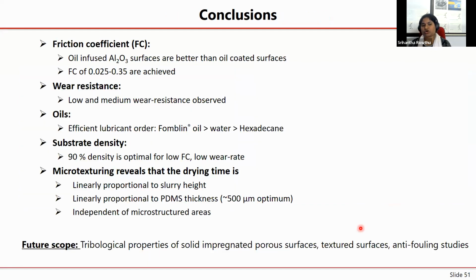All right, so we can conclude essentially that the friction coefficient of the alumina composites infused material, with 90% density, was better, right? So infused samples show a lesser friction coefficient than the lubricated samples, and values as small as 0.025 are obtained. Then wear resistance is pretty good. You have low wearing systems, you have medium wearing systems, and one can actually control depending on the application. Then we have tested, but I have not shown in this presentation, that Fomblin oil was the best lubricant. And then we also know that density-wise, 90% density was better.